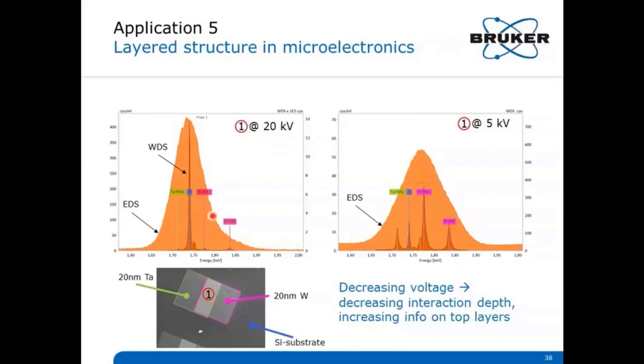At 20 keV, there is a high proportion of the substrate in the analysis, indicated by the dominant silicon peak here in the center, and only minor contribution from the top layers, tantalum and tungsten. The analysis at 5 kilovolts instead gives considerably more information from the top layers. Tantalum is marked in green, and especially tungsten, marked here in violet colors. The tungsten peaks are prominent. It can even be derived that tungsten makes up the uppermost layer, succeeded by tantalum on the silicon substrate.